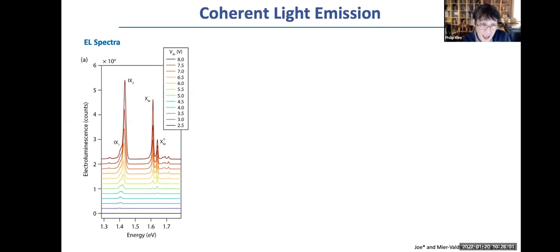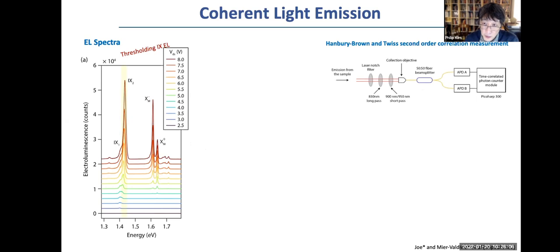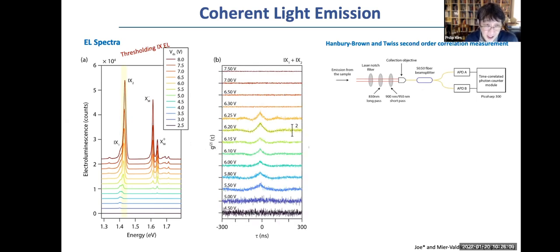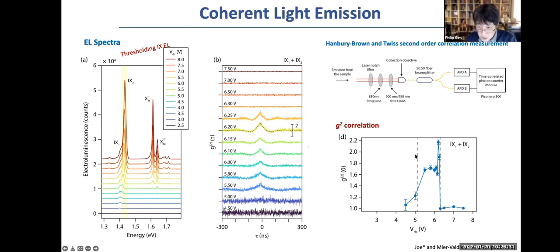Indeed, we took this light coming from the interlayer exciton and used the Hanbury Brown and Twiss second-order correlation measurement, indicating that right before the threshold behavior happens, there is an increase of the quantum correlation. So the g2 factor increases, which means a correlated effect appears in the system. But once the threshold behavior comes with a sudden increase of really bright light, you see the g2 correlation completely quenched to 1, which indicates there is a coherent process going on right after this increase of the quantum correlation.